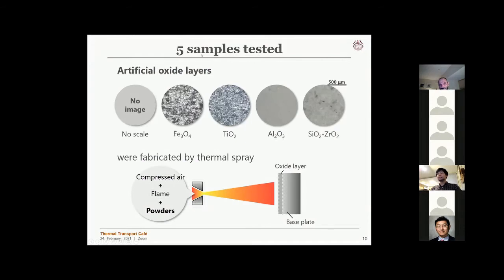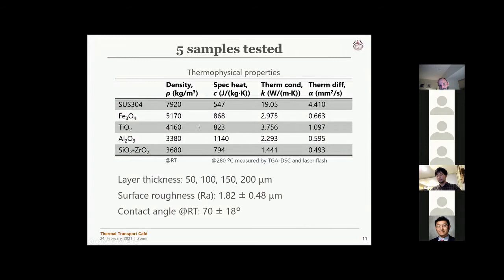We've tested 5 different samples. For reference, we had a bare stainless steel plate with no oxide scales, and 4 different compositions of oxide layers. We fabricated these samples not by oxidation, but by coating the materials using a thermal spray method. So we have 5 different thermophysical properties, and I've listed some important ones which I use later for further analysis.